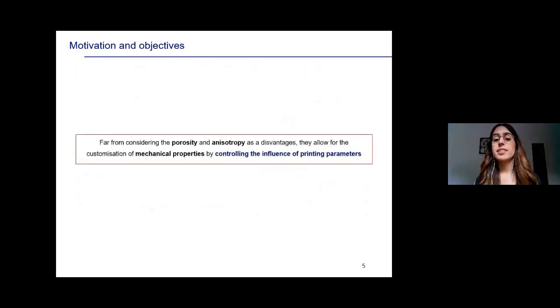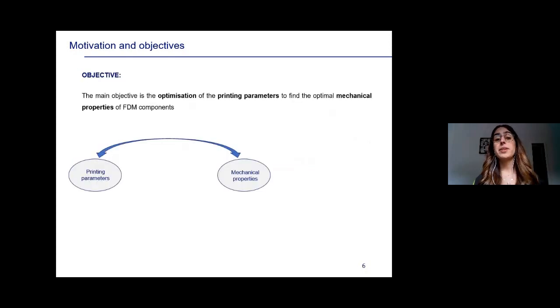However, far from considering the porosity and the anisotropies as a disadvantage, what we thought is that we can use those to produce customized mechanical properties. The only thing is that we need to be able to control the influence of the printing parameters. So the objective of my PhD was to optimize the printing parameters to find the optimal mechanical properties. That means that we wanted to propose different tools to be able to optimize these printing parameters and to find the optimal mechanical properties.